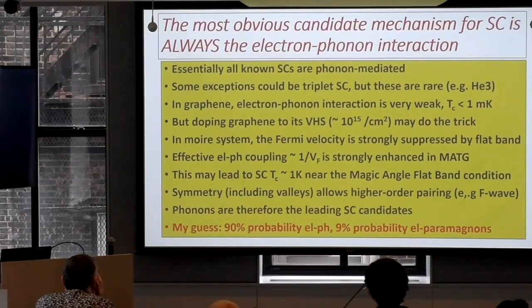I want to distinguish between what I believe and what I can show. What I believe is almost all electron-phonon. But what we can show is definitely there is one example, Bernal bilayer graphene, where electron-phonon doesn't explain the superconductivity, but electron paramagnon does. So there is still a lot to do. And now, based on what Andy just said, I cannot rule out Hubbard model physics either. We don't do quantum Monte Carlo, so I cannot do the calculation. But this should be looked into, over here where you have the facilities and the ability.